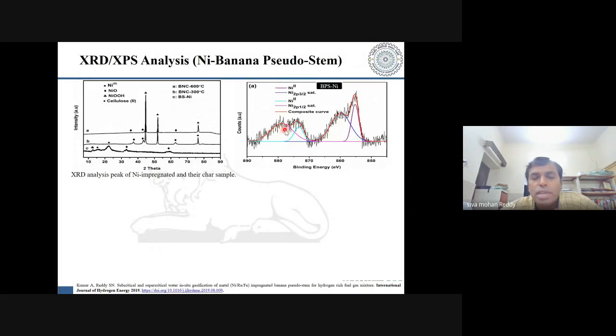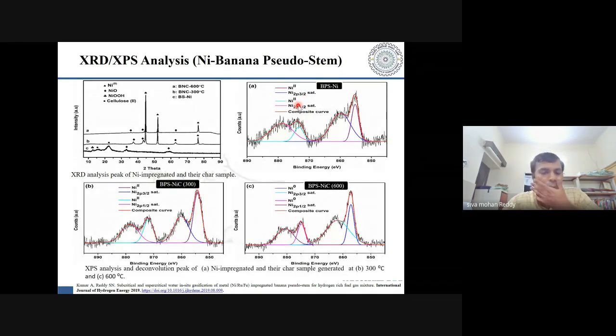which corresponds to Ni2+, that is nickel oxide particles, with the corresponding satellite peaks in light blue and dark blue color. Okay, so these binding energies convey that the nickel existed in the form of Ni2+ in the raw biomass that you are talking about. This is banana pseudostem impregnated with your nickel. Then if you look at the char that is formed, instead of a spread-out composite curve, you have sharp intense peaks, and when deconvoluted, you still see that nickel exists in the form of Ni2+ for the corresponding binding energies reported with the impregnated biomass.